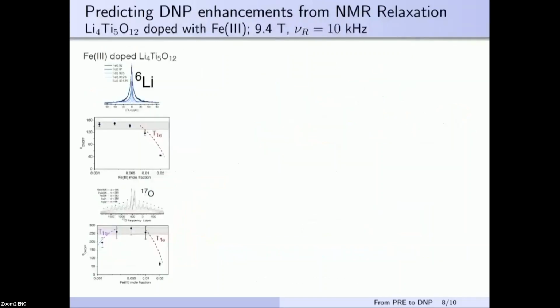I'm going to show you a few experimental examples. This is iron-doped lithium titanium oxide. Here you can see the DNP enhancement for lithium-6 and for oxygen-17 at natural abundance versus the iron concentration. One interesting thing that we observed is that the enhancement is, over a large range of concentration, independent of the concentration of iron. The reason for this is just what I told you before, that the DNP enhancement is independent of the distance. So if we increase the concentration of iron, of polarizing agent, we are merely reducing the distance, which will give us faster buildup times, but not higher enhancements.